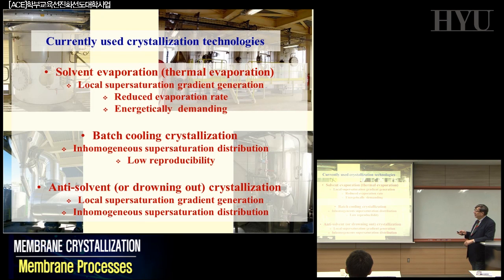If you eliminate and reduce the presence of the solvent, you concentrate your solution. At one point, you are approaching saturation. And when you approach saturation, from a homogeneous system you arrive at a heterogeneous system where the solid phase can precipitate. At a certain temperature, this is a dynamic thermodynamic equilibrium: you will have equilibrium between the solid phase and the solution, in which there is a continuous exchange of molecules going from the liquid phase to the solid phase and vice versa.